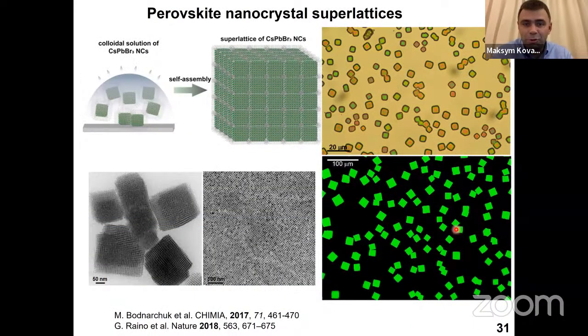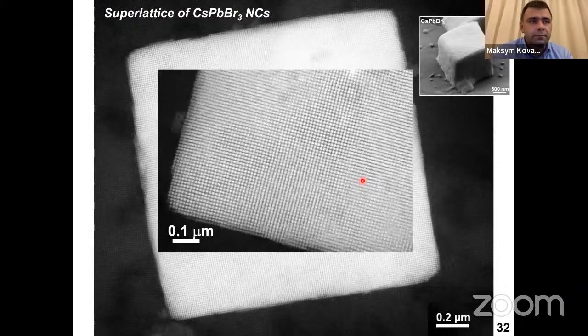Now you can ask, what about cubes? For cubes, it's much simpler. Cubes form supercubes, which is 100% space occupation. And so naturally, these were the first superlattices whose optical properties we examined at low temperatures. So these large supercubes can be as large as 10, 20 micron, and they can be produced as single entities on the substrate. And this is an electron microscopy of these.